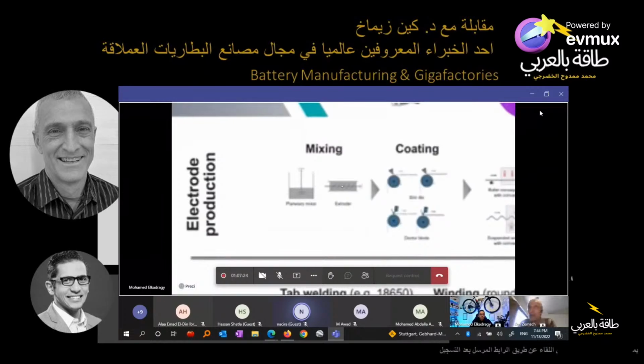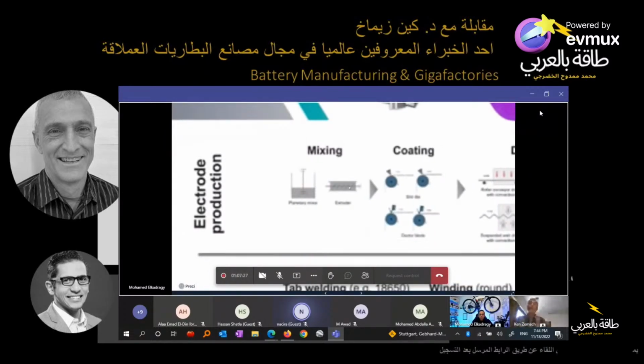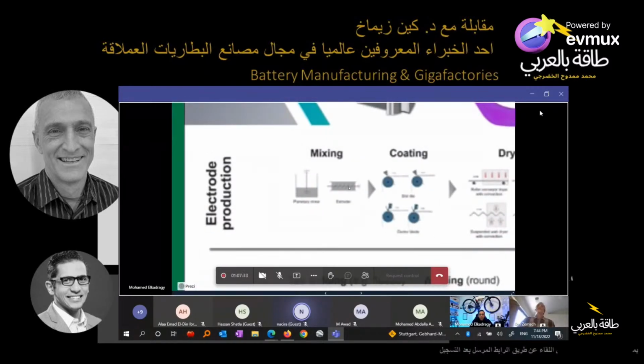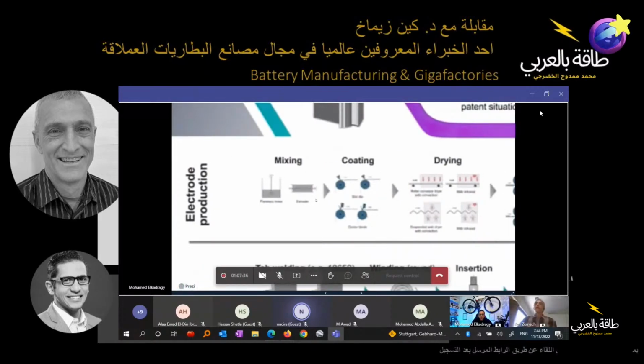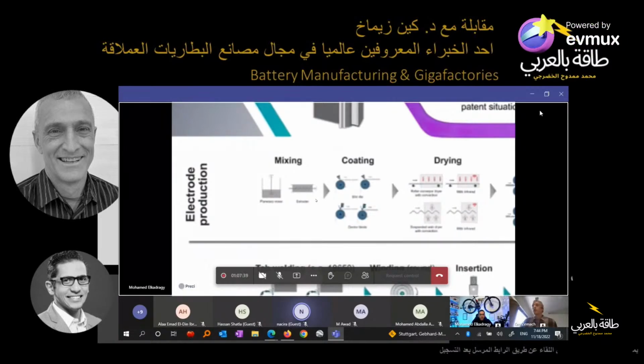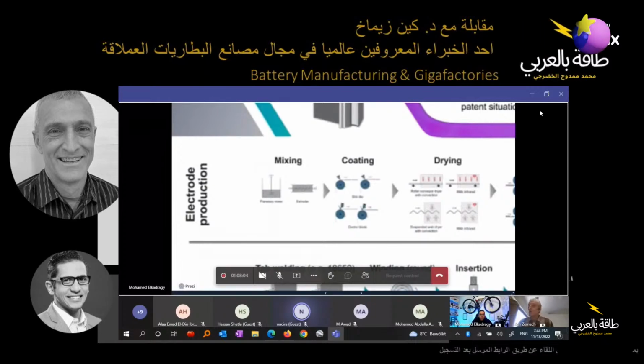So the next thing that you do, now that's the anode. The cathode, I don't want to get too detailed. Electrochemically, in a lithium-ion battery, carboxymethylcellulose and styrene butadiene rubber, those things that were soluble in water, are not electrochemically stable on the cathode side. In other words, electrically and chemically, they break down because of the electric potential. So you usually use a fluorinated binder. It's got fluorine on it, which makes it really expensive. But those aren't soluble in water. So now you can't use water as your solvent.